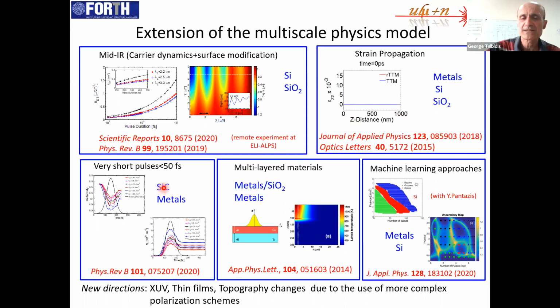Also, we wanted to see what happens if we use very short pulses, less than 50 femtoseconds. We saw previously that the electron system gets excited, and we have electron excitation and relaxation of the electron system through electron-electron scattering. If we look at this regime, below 50 femtoseconds, the theoretical framework shows that we have the production of a non-thermal electron system that interacts with the electron system which is in thermal equilibrium, but also we have interaction of the non-thermal electron system with the lattice system. So we want to see the response of the material in this regime.